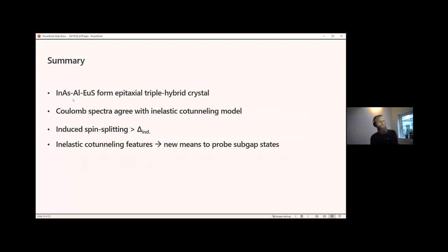I showed to you that the indium arsenide aluminum europium sulfide can form a nice epitaxial triple hybrid crystal. And then using these crystals to form Coulomb islands, we find spectra that agree well with the models of inelastic cotunneling through a spin-polarized subgap state.